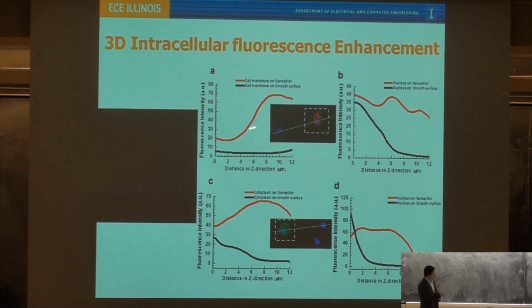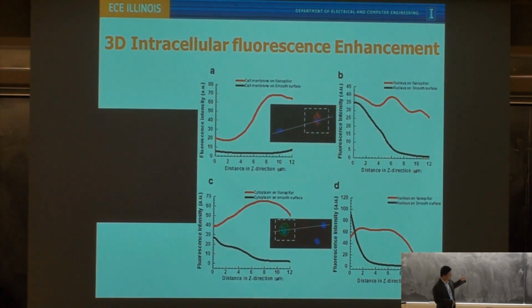So we do a quantitative analysis of the fluorescent intensity on the cells at different Z locations. We see that the fluorescent enhancement is happening not only on the surface, but also well above the surface. And the maximum enhancement with respect to the smooth silver surface is about 70 times. If you calculate the actual enhancement factor with respect to the glass slide or petri dish, that's over 100 already.